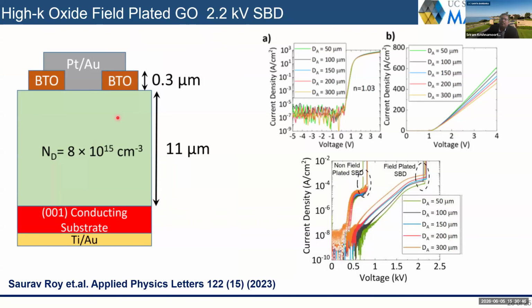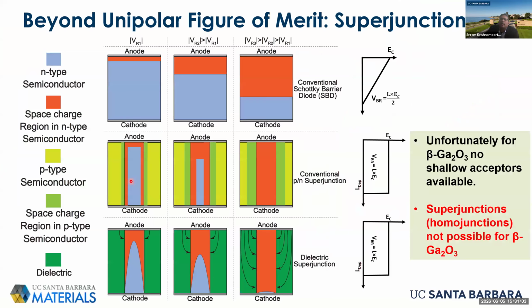So these devices still have a triangular electric field profile because when you deplete the charge, you have uniform charge, and you use Poisson's equation or Gauss's law. So basically, you will find the electric field is linear. You have a triangular field profile. But in silicon, you can actually do charge balancing. So essentially, you can have columns of p-type and n-type material, which if the charge is equal, then you can get a net zero charge in the depleted layer, which results in a flat or a constant electric field profile, and that gives you twice the breakdown voltage. So that's the concept of a silicon superjunction.